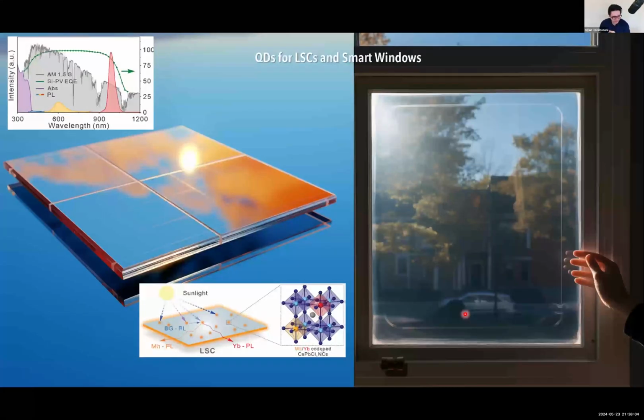Now, most recently, we wanted to see if we can use our autonomous fluidic labs to discover the best-in-class quantum dot for a specific application. And we were interested in smart windows and solar cells specifically. There's one class of quantum dots called cation-doped metal halide perovskites that are really good at absorbing deep UV light and then converting it to visible light and near infrared region, which silicon panels are pretty good at absorbing, but they're not really efficient in absorbing deep UV. So our goal was, can we find the best-in-class metal cation-doped perovskite quantum dots for applications in the smart windows and solar cells?